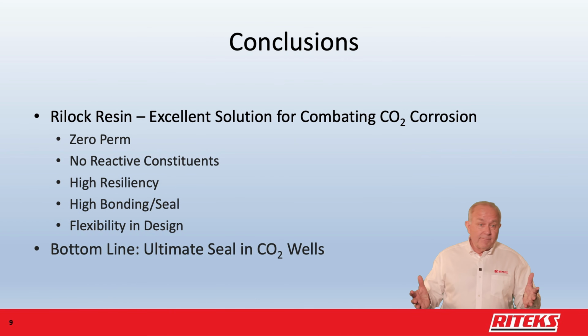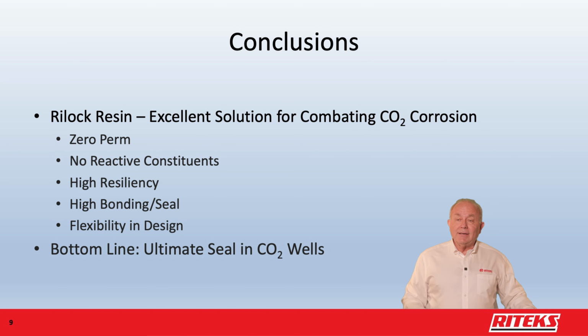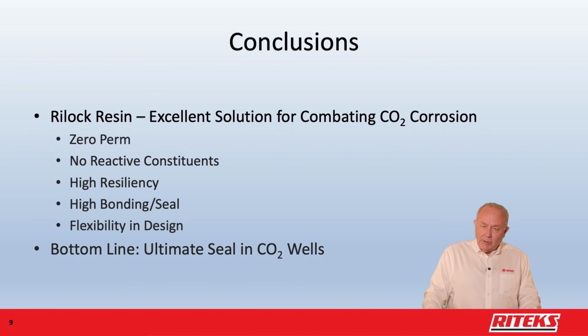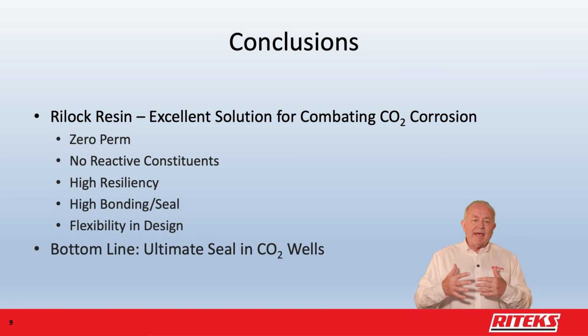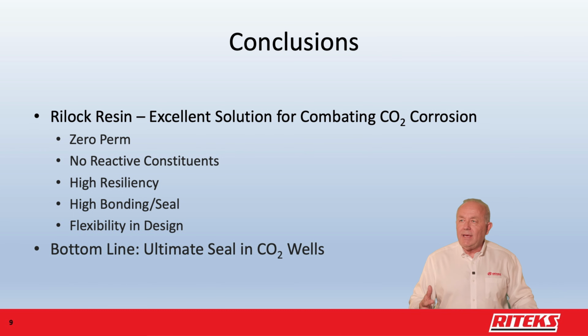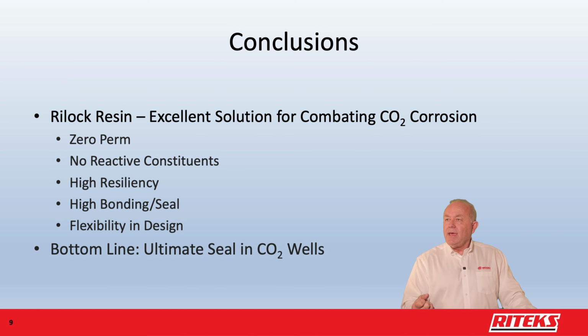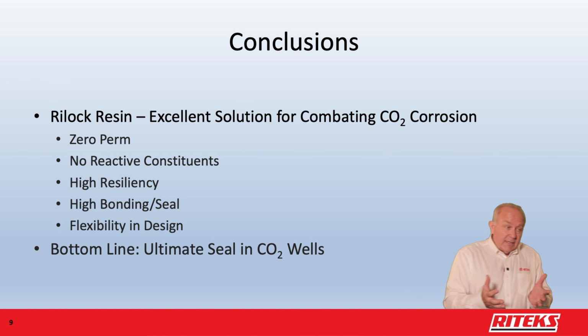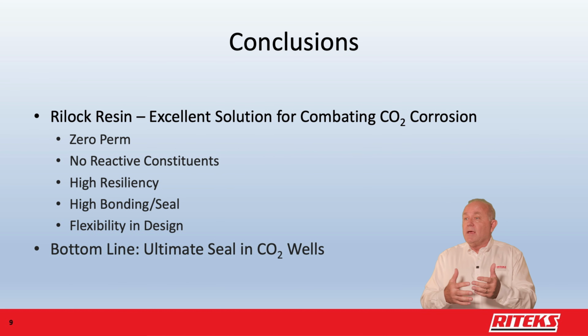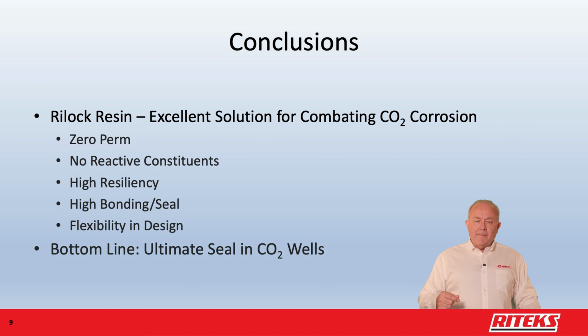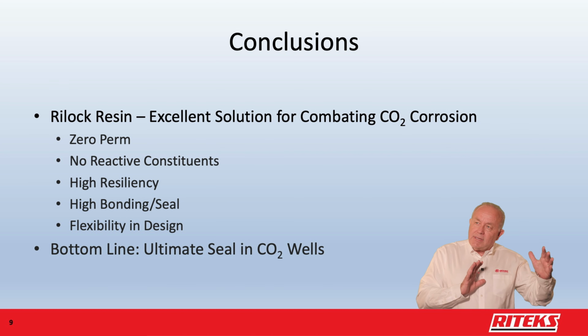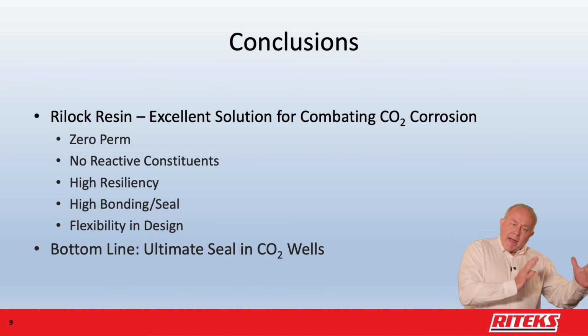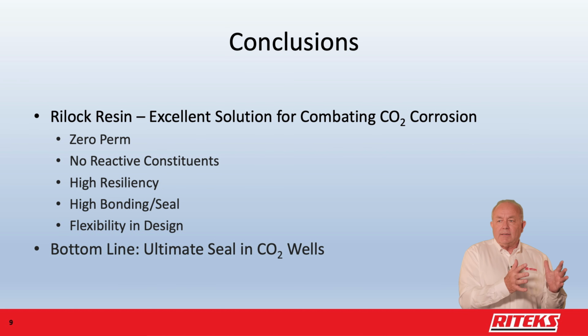So in conclusion, RiLOCK resin, guess what, is an excellent solution for combating CO2 corrosion. Why? Because it has all the properties that we need. It has 0 permeability. It has no reactive constituents, therefore it cannot corrode. It has very high resiliency, so it's resistant to stress and repeated well interventions. It has high bonding and seal, doesn't allow for there to be microannulus or lack of bond in both the formation and the pipe.